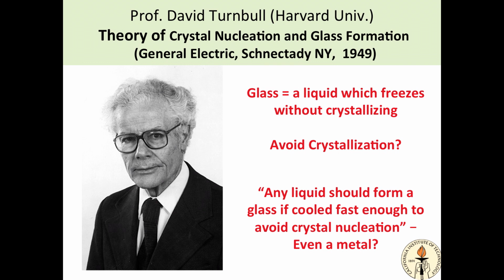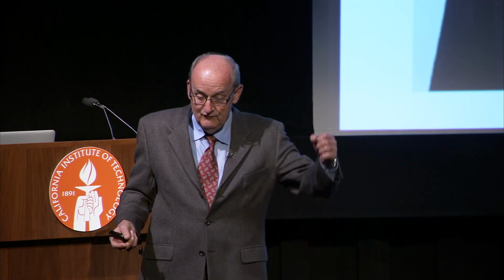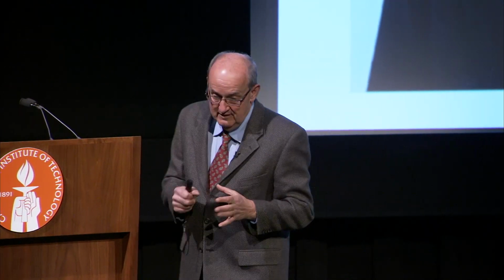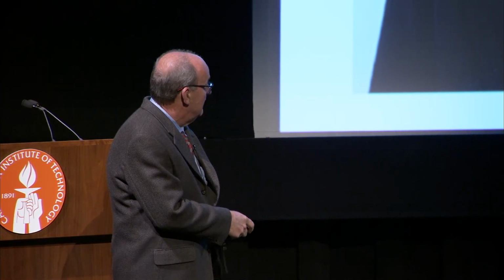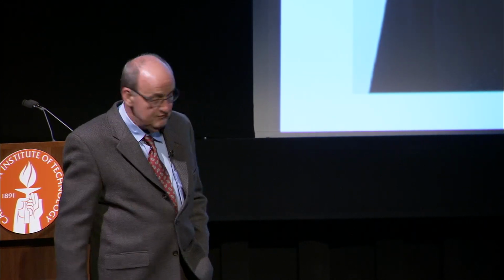Turnbull concluded, after 3 or 4 years of working on this problem, that any liquid, including a metal, would form a glass if you cooled it fast enough. In other words, the formation of embryos takes time, and if you can cool the liquid down and freeze it, solidify it, set it up, vitrify it, those are the terms we use for glass blowing and all that. If the liquid freezes, then no crystal is formed, and we got a glass.